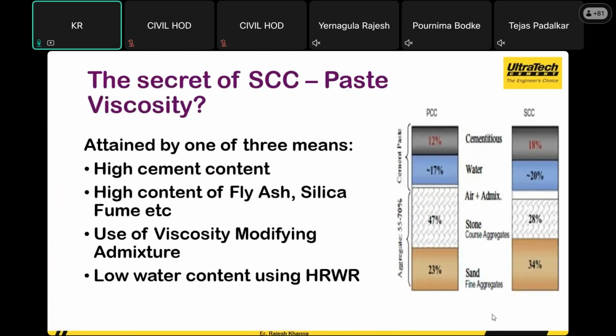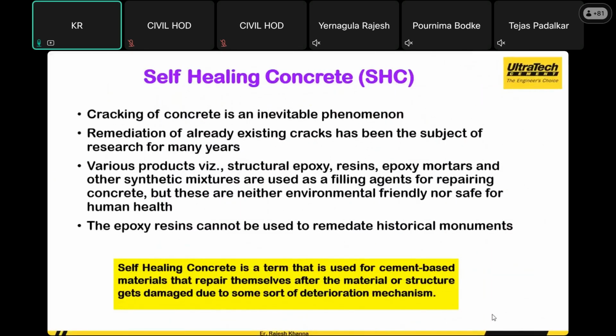And the mix also has a different secret. I would say it is a real miracle to the engineering fraternity, that if you want to send a concrete to any nook and corner of any different architectural shape, with this concrete you can achieve it. This is the secret of self-compacting concrete: more fines and less coarse aggregates, so that using viscosity modifying agents or lower water content by using high range water reducers, you can achieve these self-compacting properties within the concrete, so that you can leave the concrete to flow on its own.